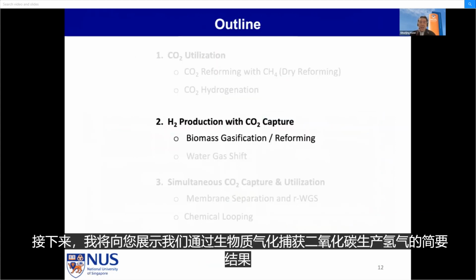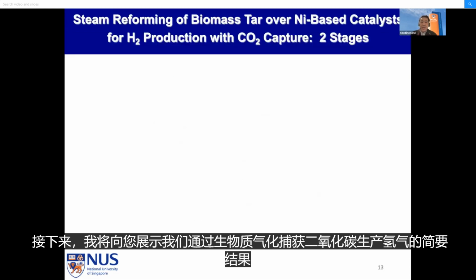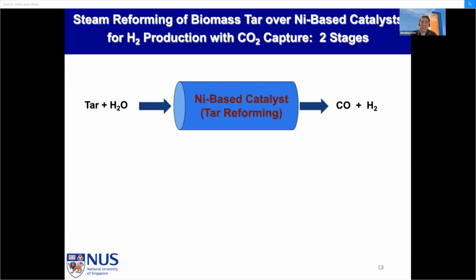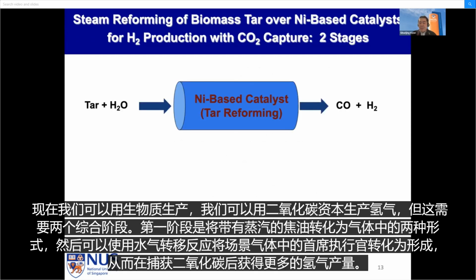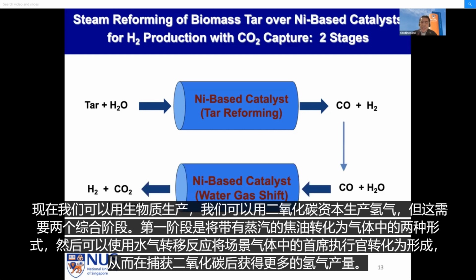Next, I will show you a brief result for the hydrogen production with CO2 capture from biomass gasification. Now, from biomass we can produce hydrogen with CO2 capture, but it requires two integrated stages. The first stage is to convert tar with steam to form syngas, and after that, the CO in the syngas can be converted using the water gas shift reaction to get more hydrogen yield with CO2 captured.